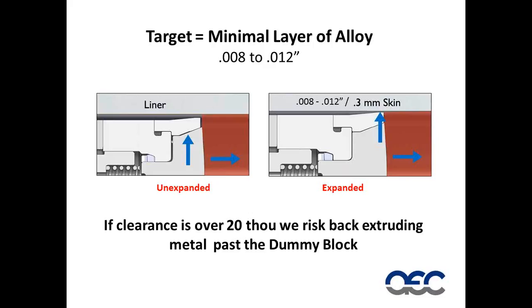The goal when the dummy block is expanded is to leave a skin thickness of somewhere between 8 to 12 thousandths of an inch. And ideally, we would like this to be uniform thickness all around the ID of the liner. What we do know today is if that gap becomes greater than about 20 thou, there's a risk of extruding metal back past the dummy block.